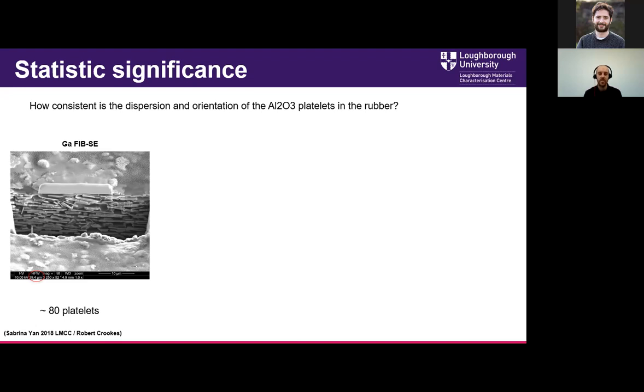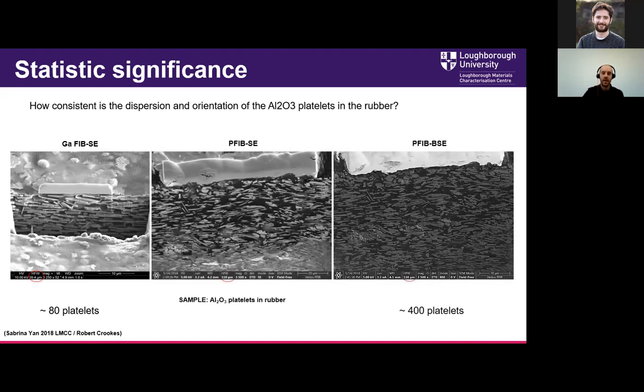It's a nice data set, but it's not hugely useful if we want to do some deeper analysis. And this is where having a FIB source where we can go to higher currents comes in handy. If we can go to a higher current, we can cut a larger area cross section in a similar time period. And suddenly we have a more statistical data set. So we go from looking at 80 platelets up to looking at 400 platelets. And suddenly we're starting to be able to identify a more statistical trend of what's going on. So we might see at the surface, there's a certain type of structure, and then further into the bulk, we get something a bit different, more uniformity, for instance.